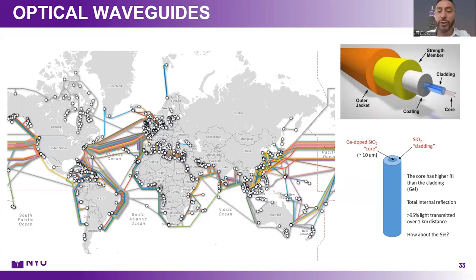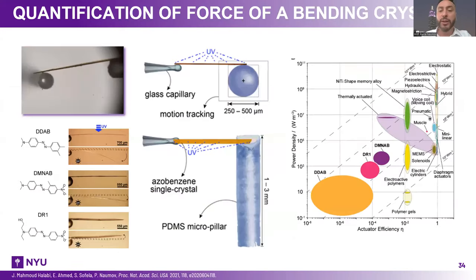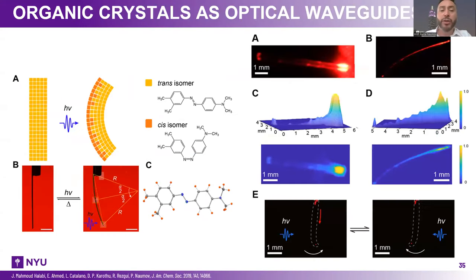And as you know, all the information that you are looking at on the screen comes from my country, from Macedonia, where I am now, through these optical fibers. And the idea is to look for new materials, because the optical fibers are robust. They are made from inorganic materials, but they're not chemically versatile. We don't have much chance to play with their composition. So what if we replace this with organic crystals? This is one of the examples that I showed you before. We can use the crystal as an optical waveguide. So I'm going to skip this slide. But perhaps this example is more important, because now we have photochemically responsive crystals. So it can react, it can bend under UV light on one side and collect it to the other side.